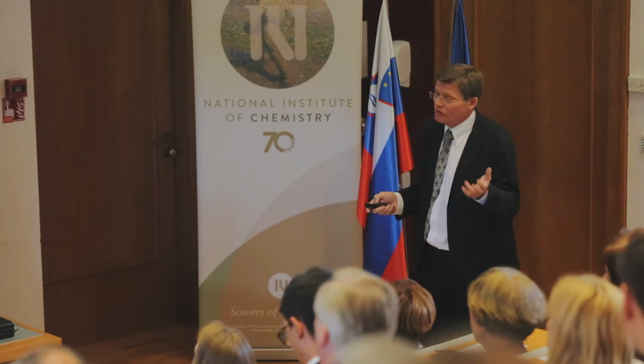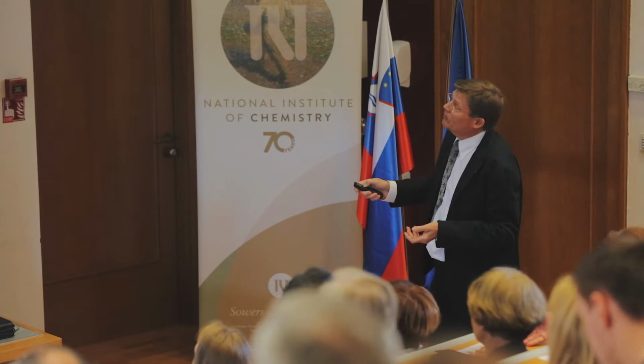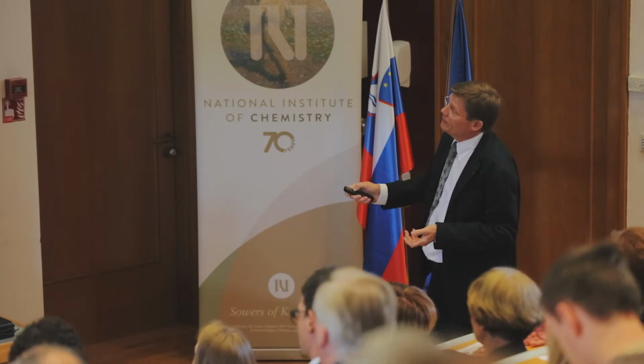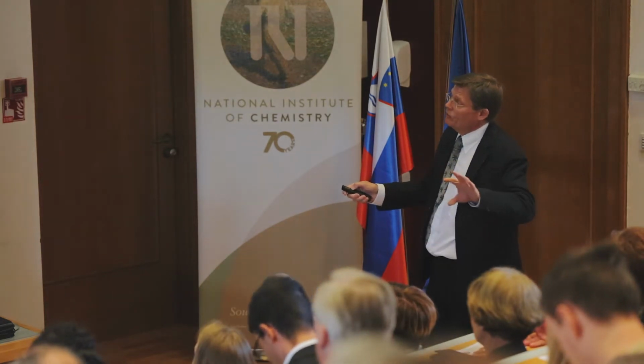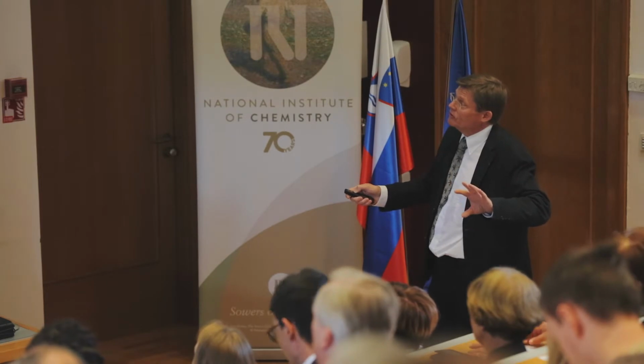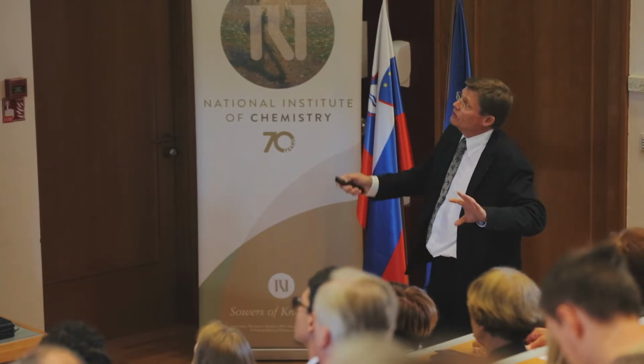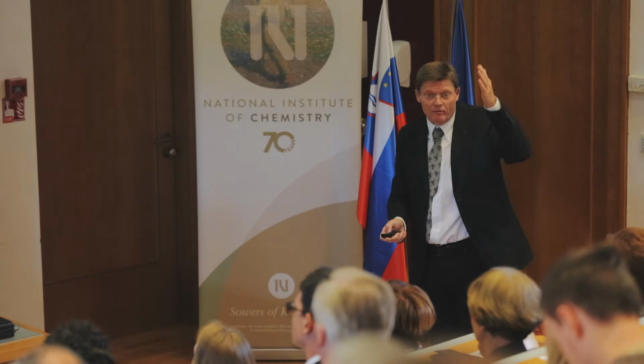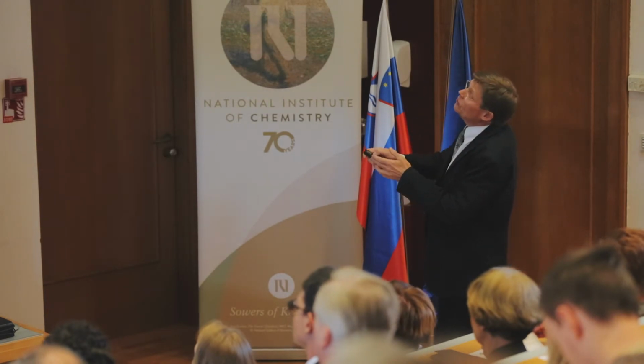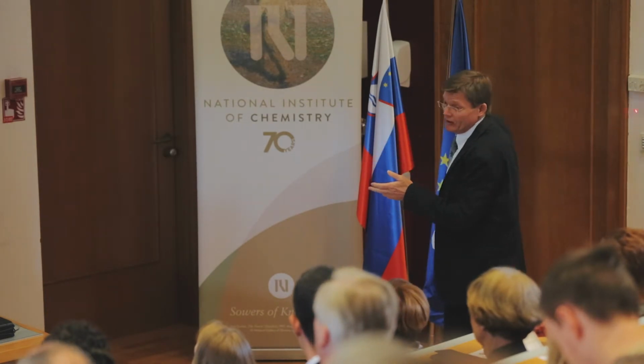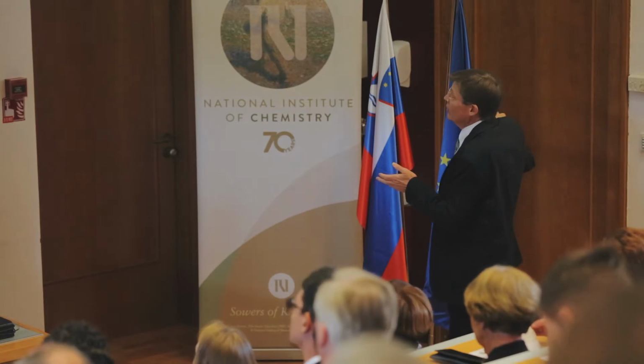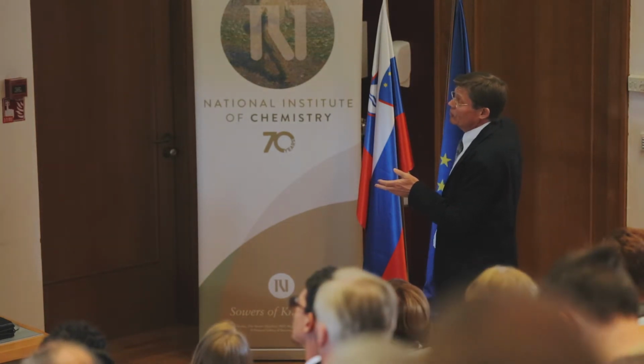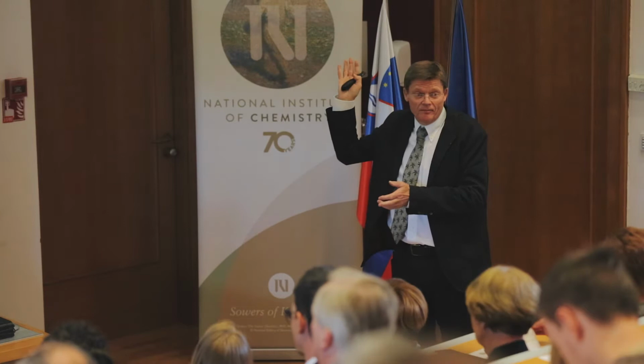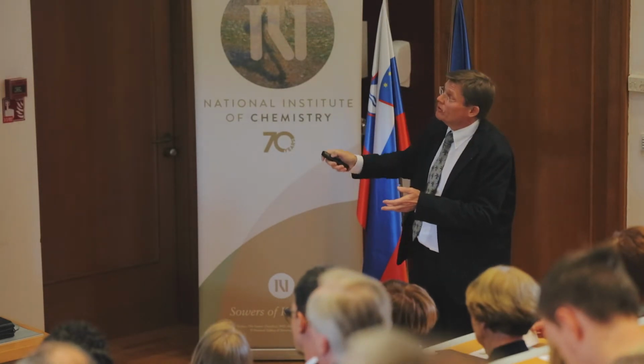If you ask an electrical engineer, he will say, oh, this comes out. This is the bulk, at high frequencies where you don't perceive this kind of blocking effect, and then this is just a capacitor. You can say this is a huge semicircle which is infinitely large, and the diameter, which finally ends up in the electronic resistance, is just infinitely large. This is a typical capacitor function.